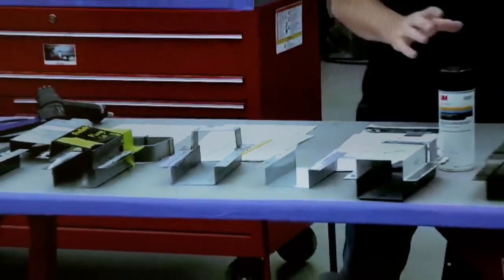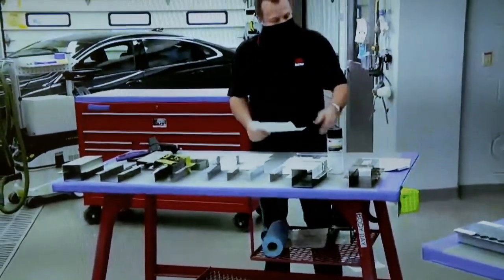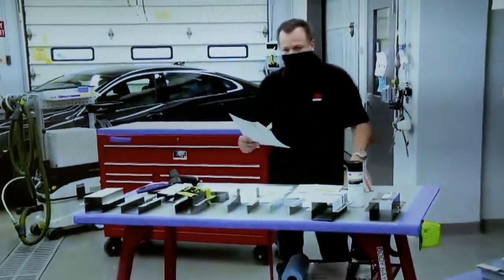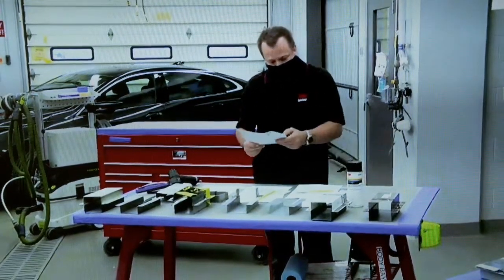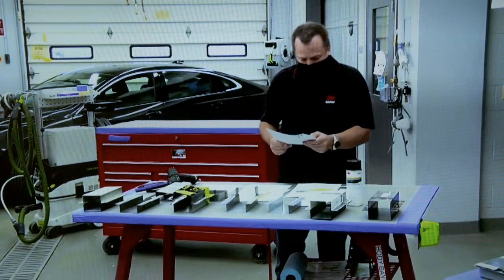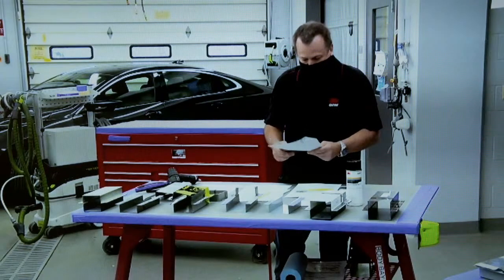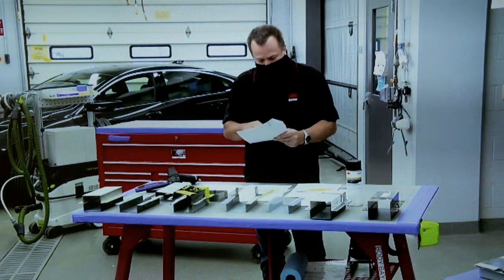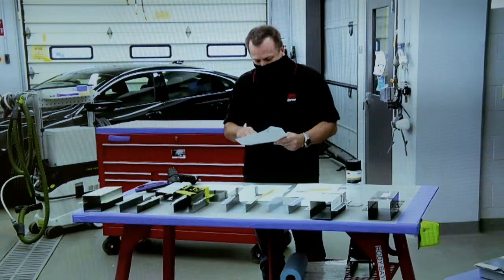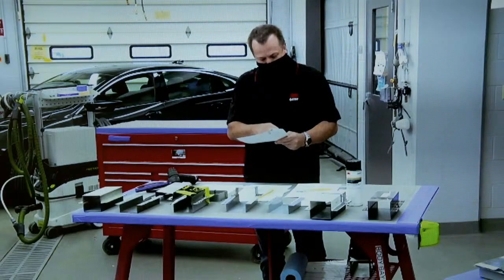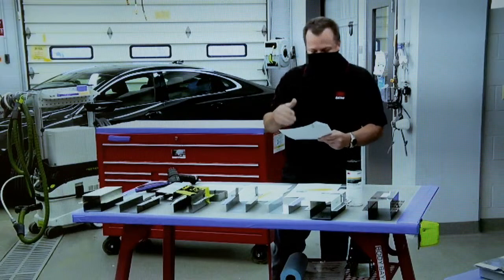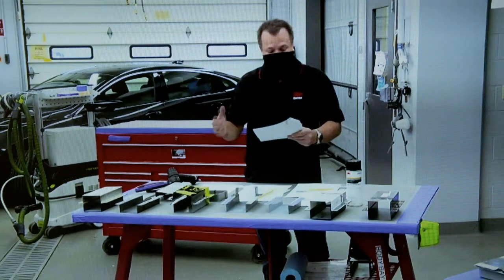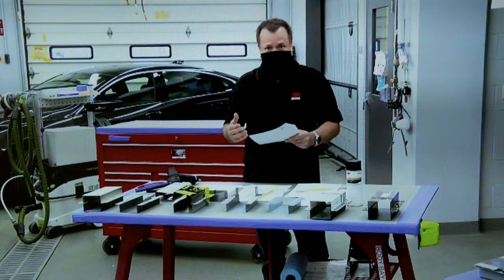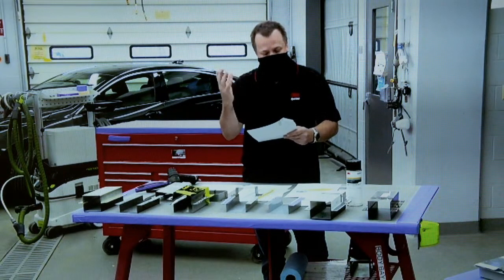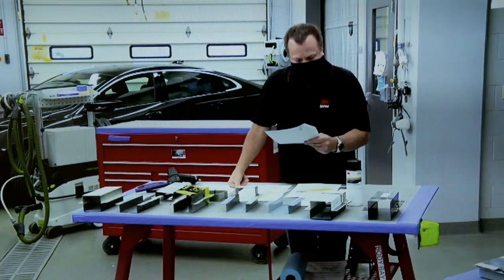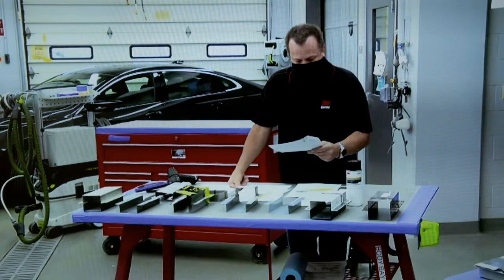So, again, what do the OEMs say? Well, there's two of them I have here that I thought I'd point out. This is from JLR, and JLR says it's important for the weld quality that the inner area is bare metal. First of all, they say don't use zinc weld through primer. And then they say zinc and paint residues in the weld area burn and cause serious hole formation during welding. When they say hole formation, I think it's a translation thing. They mean porosity. So welding over weld-through primer makes welds porous. Zinc gets into the molten weld puddle, causes all kinds of porosity. They say if the zinc layer and the paint coating are not removed, the zinc paint will burn during welding.